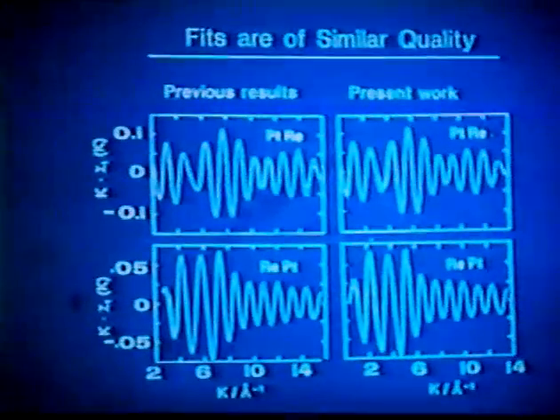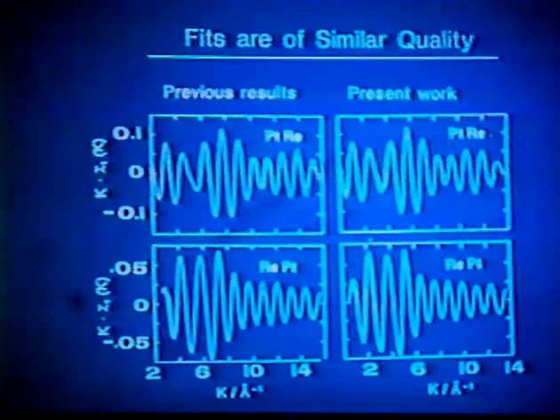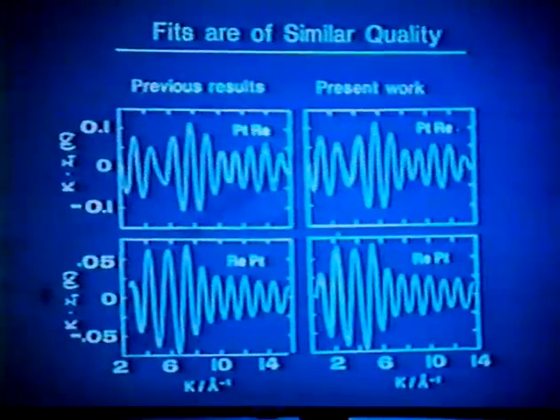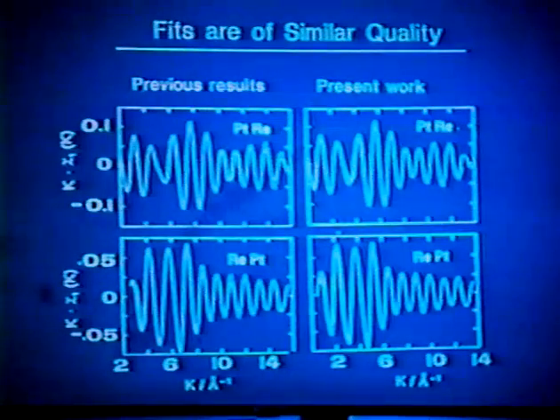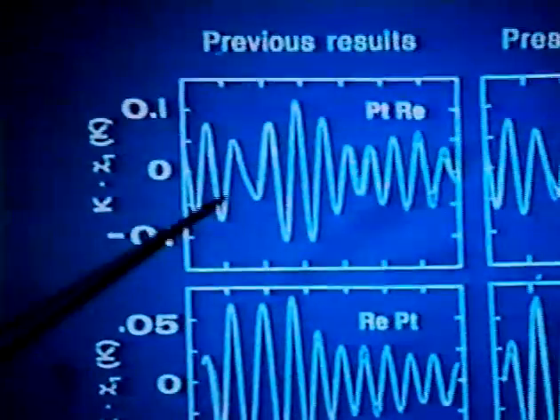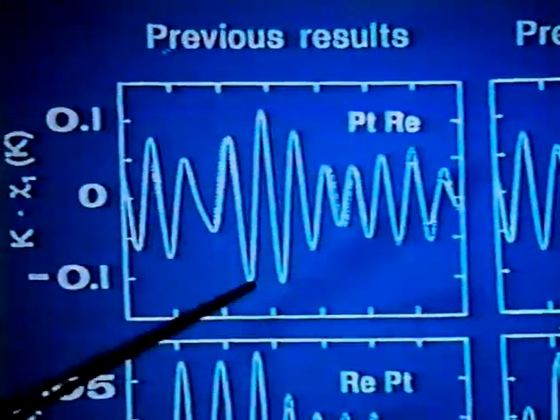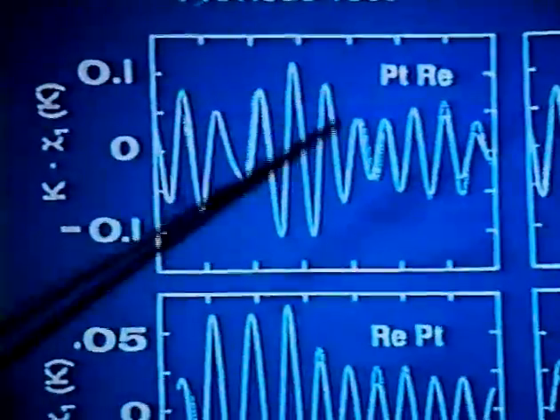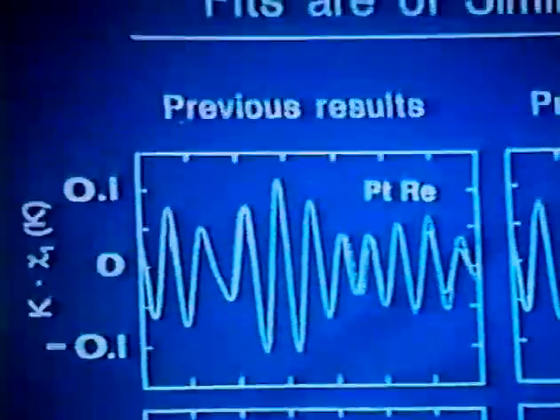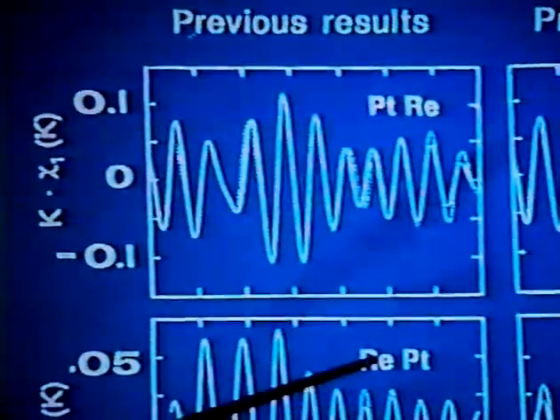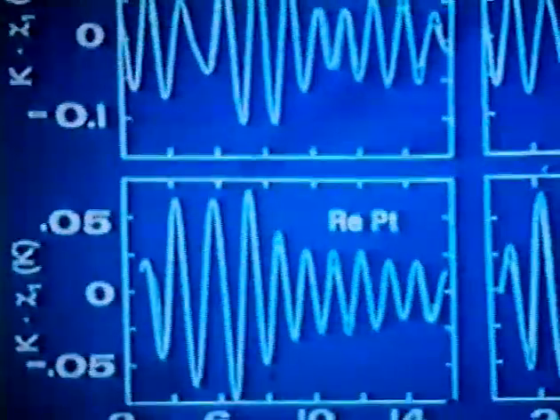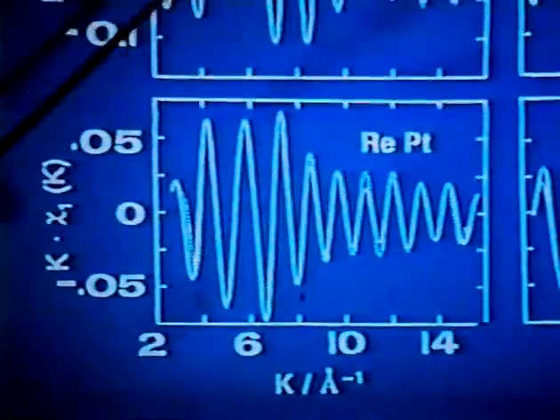Now, one of the interesting things, this is a fitting exercise. We get our parameters by a nonlinear regression. And so previously, for analyzing two spectra, we had 12 adjustable parameters, 13 really. And our calculated spectrum versus our actual data looked like this. It's a damn good fit. This is a fit to the platinum spectrum. This is a fit to the rhenium spectrum.